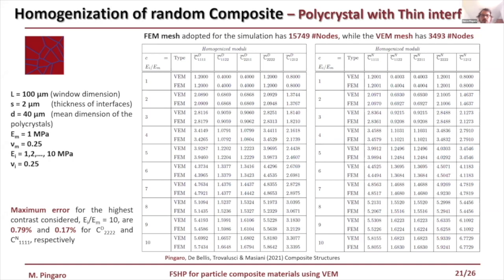In the two tables are reported the homogenized elastic moduli for different levels of contrast, in the case of the Dirichlet boundary condition and in the case of Neumann boundary condition. As you can see in this result, the results are very good, and the maximum error is less than 1%, with a high reduction of computational cost. In the upper part of the slide, I reported the number of nodes used for the two different meshes.